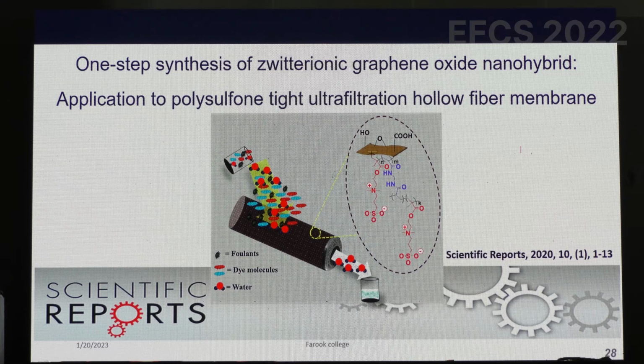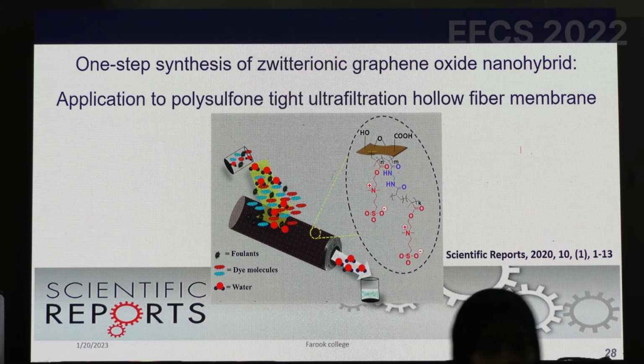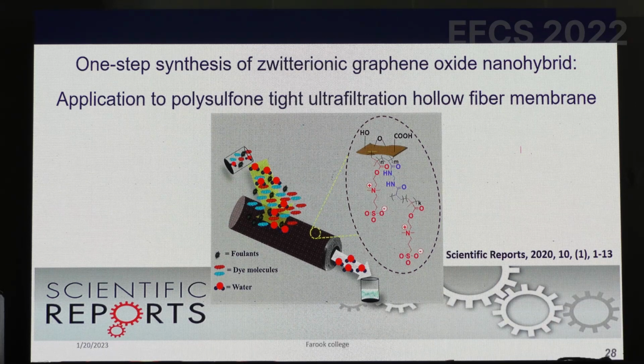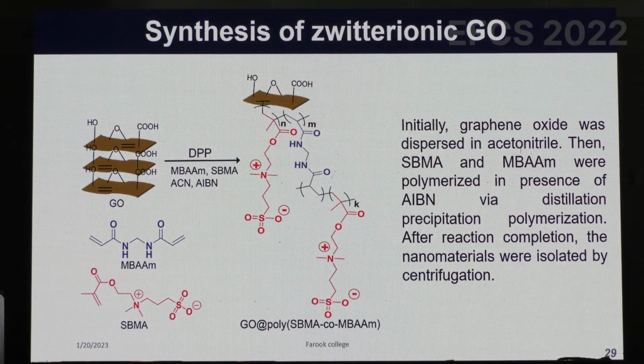And then again, many researchers, as you know, particularly in the last 10 years, are working on graphene or graphene oxide. Again, we wanted to improve the performance of these materials to a higher extent. In this one, the strategy we employed was that the graphene oxide was synthesized separately in the laboratory, and then this graphene oxide was decorated with the zwitterionic polymer nanoparticles. And as we expected, the performance was much superior to that of the previous material. So this is the synthetic scheme for the preparation of the graphene oxide decorated with these zwitterionic nanoparticles.